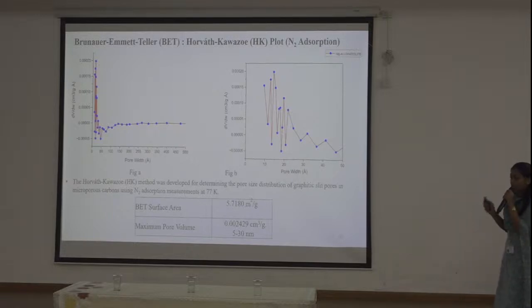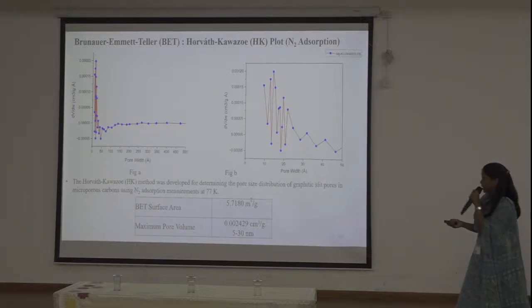We use BET to calculate the pore size, and here the maximum pore volume was found to be 0.002429 centimeter cube per gram, with pore volume ranging from 5 to 30 nanometers.